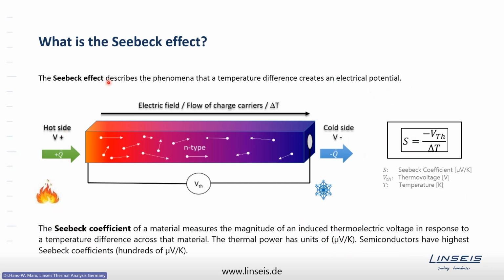So the Seebeck effect describes that a temperature difference creates an electrical potential. If you have a thermoelectric material, you heat it on one side and cool it on the other side, you can harvest and measure a voltage. The Seebeck coefficient is this voltage between the hot and the cold side divided by the temperature difference between them. So this voltage is a response to the temperature difference across a material. It's measured in volt per Kelvin or microvolt per Kelvin. The highest Seebeck coefficients are found for semiconductors, which may have Seebeck coefficients of hundreds of microvolt per Kelvin. Metals are much poorer thermoelectric materials.